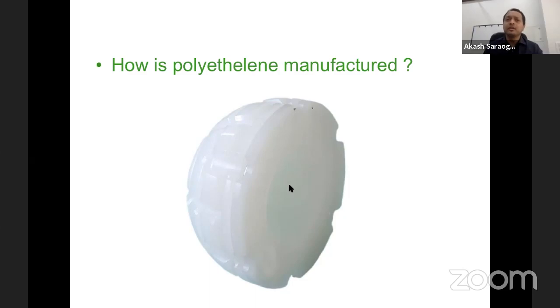So what can we do if we cannot melt the plastic? We can do a procedure called annealing. Annealing means heating the plastic, not to the extent that it melts, but sub-temperature annealing of the plastic. It will take away the maximum number of free radicals by this heating of the plastic, but not all.